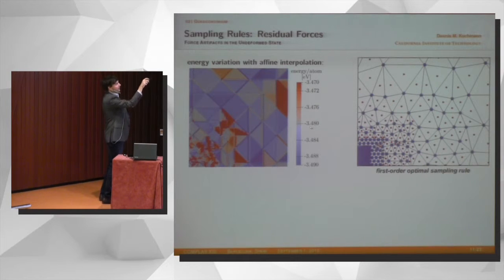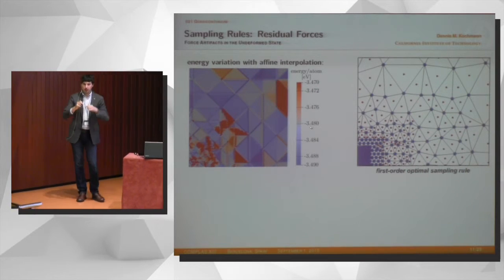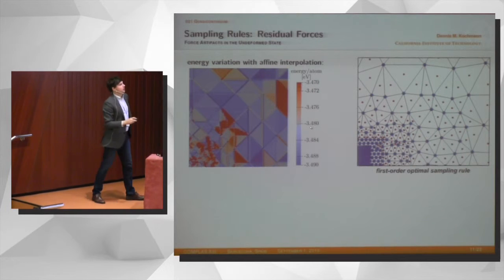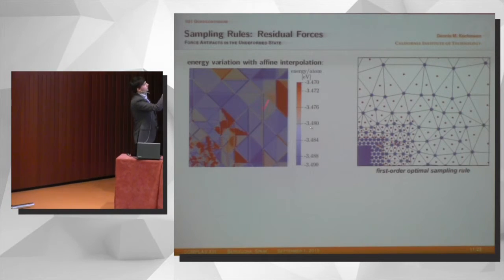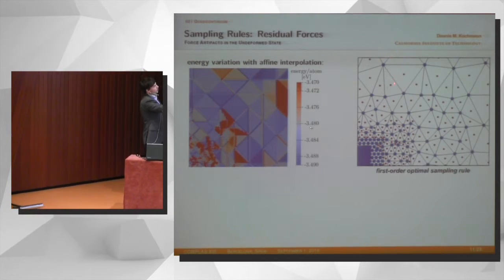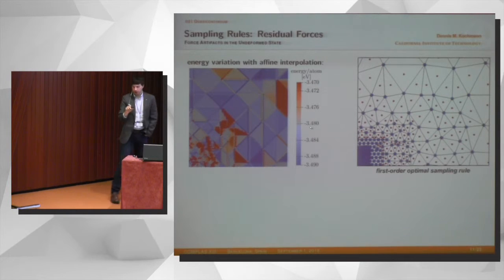Of course, as you go towards the edges, you start to see the deformation of the neighboring elements, and so the energy changes. And so by doing what we do over here, we actually take this into account. Namely, we have only one sampling site, a quadrature atom on the inside, which senses the energy of all the points on the inside. And then we have additional ones on the nodes, which feel what's happening on the nodes.